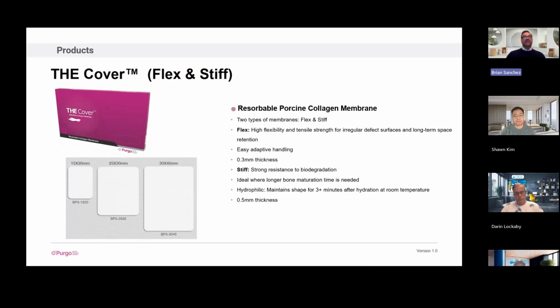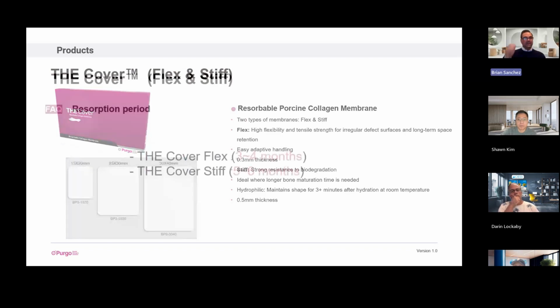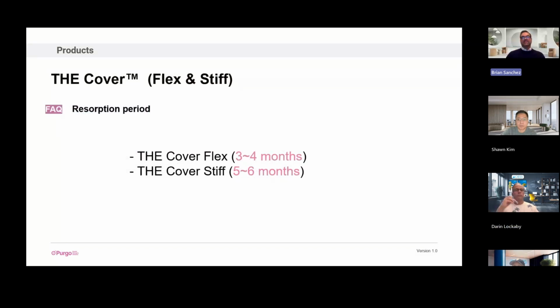So the Cover Flex is 0.3 millimeters thick and comes in a 15 by 20, a 25 by 30, or a 30 by 40 offering. And then we have the Cover Stiff, which has strong resistance to biodegradation. So it's ideal where longer bone maturation time is needed. It's hydrophilic, so it maintains its shape for 3 or more minutes after hydration at room temperature and is thicker than the Flex. It's 0.5 millimeters thick. And there's a reason why there are two different thicknesses. The Cover Flex resorption period is around 3 to 4 months because it's 0.3 millimeters, and the Cover Stiff, which is the 0.5 millimeter, has a 5 to 6 month resorption period.